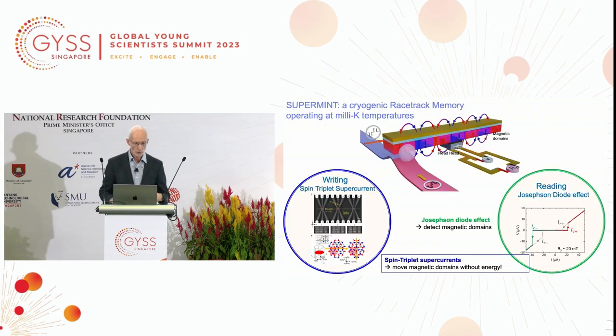So my current program is we want to build a super mint or super track, a cryogenic racetrack memory, which would basically consume very little energy. We would create triplet supercurrents in very special ways, pass them into the racetrack, they would deliver angular momentum, the domain walls would move, and we would detect them using this Josephson diode effect. So we think this is a very interesting concept, and we're working hard on this.